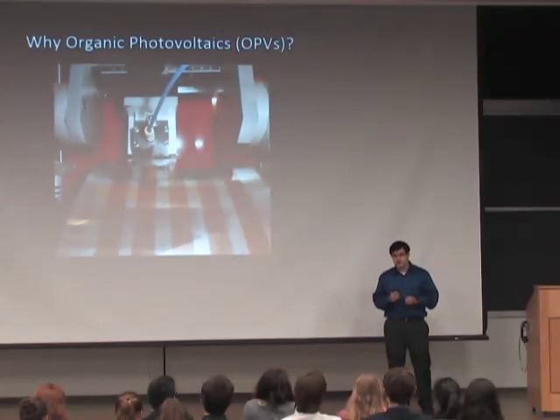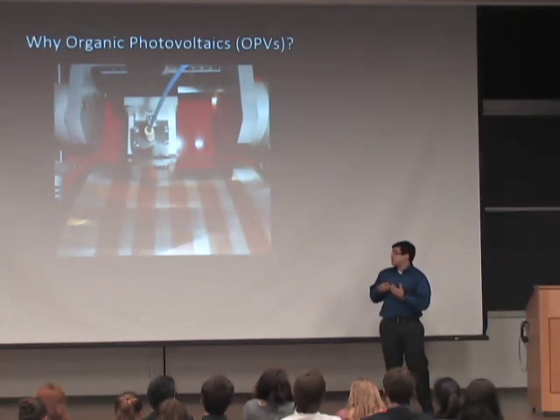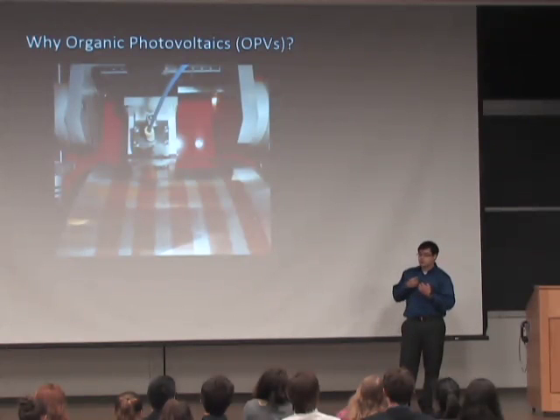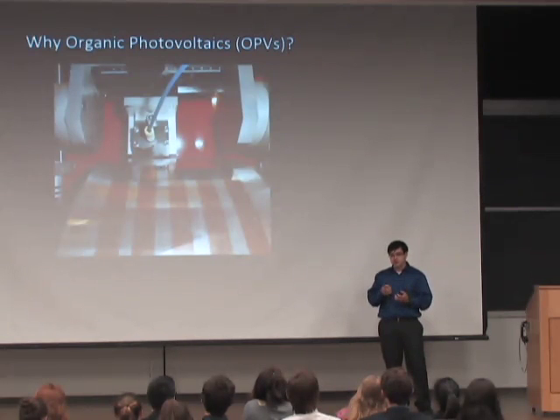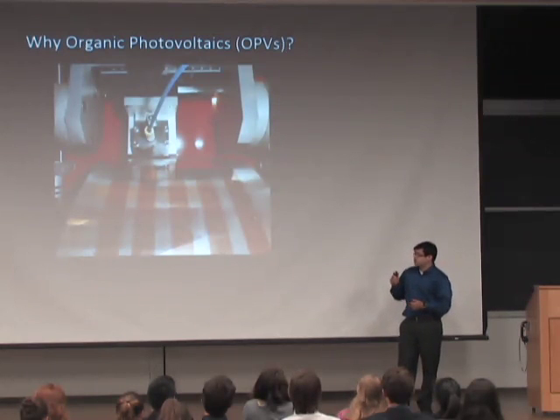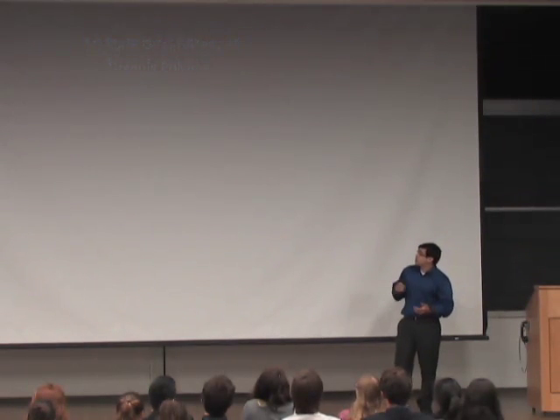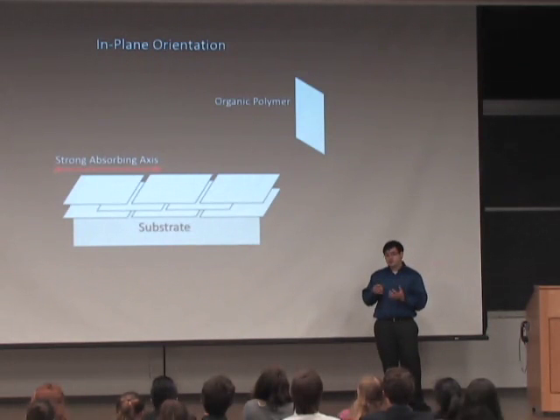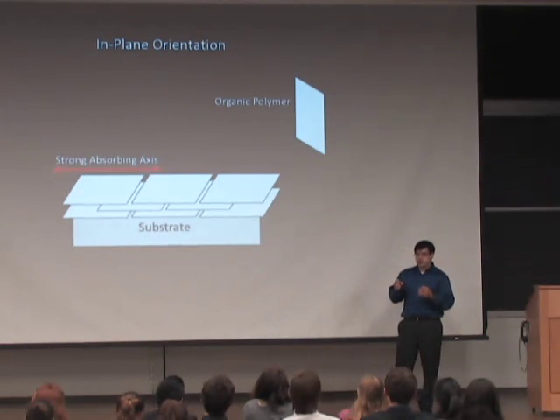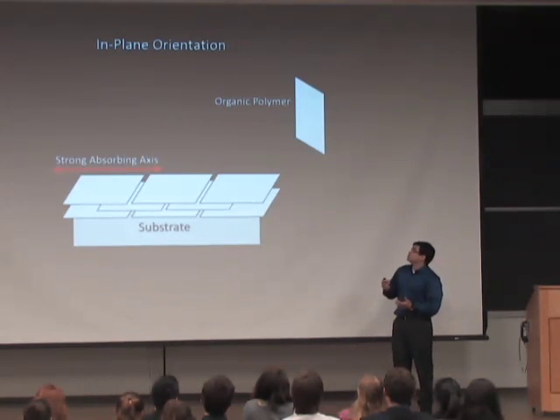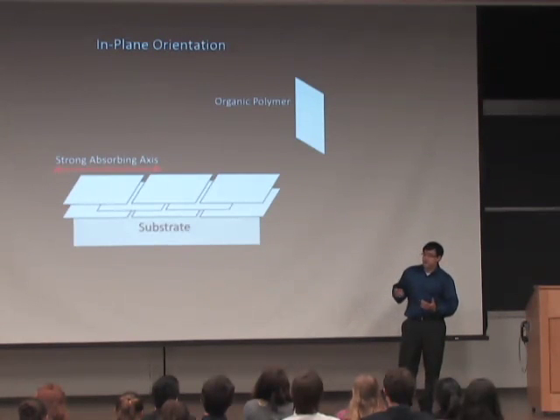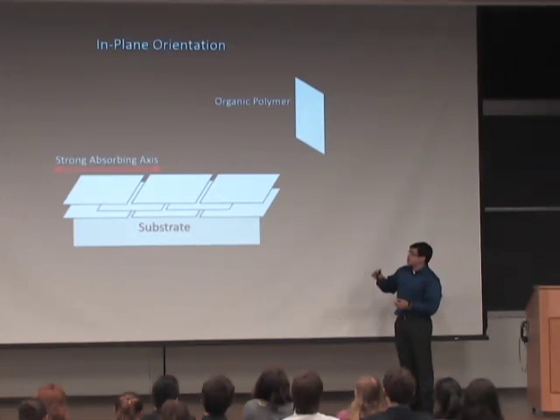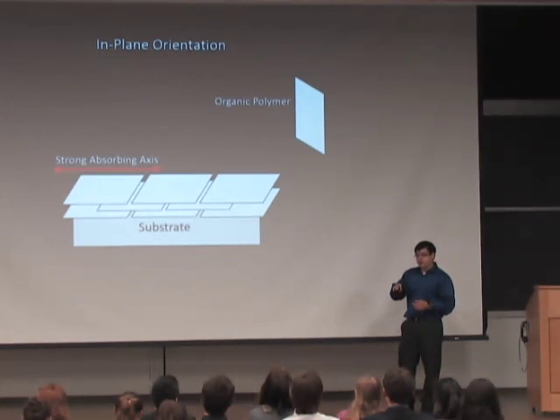So what the Schuler group wants to do is find a new approach that can enhance efficiency, and this approach we theorize to be taking advantage of optical anisotropies or directional dependencies in organic polymers and optimizing them so we can enhance efficiency. So what that looks like is some organic polymers have different orientations that are process dependent and can form these orientations depending on how you apply them to your sample, whether it be in different solutions or different concentrations of things. So here's one orientation, for example, an in-plane orientation where the organic polymer's strong absorbing axis is aligned parallel to the substrate.